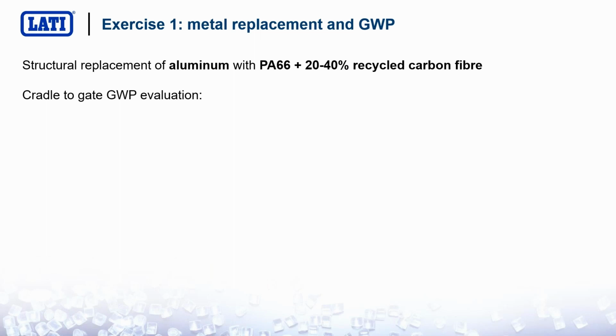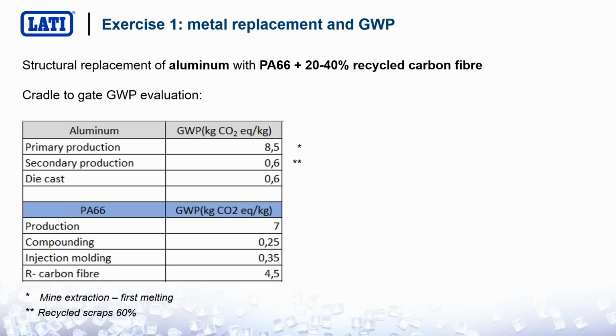Now, let's translate this exercise from structural metal to structural plastic, and let's evaluate the global warming potential reduction. Let's evaluate the cradle-to-gate global warming potential of aluminum and plastic. In the chart you see here, you can see actual numbers which can be found in the literature. For aluminum, I wanted to include 60% of scrap aluminum in a die cast. So the global warming potential for die cast aluminum featuring 60% recycled is more or less 4 kilos of CO2 equivalent per kilo. Remember this number, 4 kg of CO2 equivalent per kilo of aluminum using 60% recycled. I know that today some die cast can be 100%, but let's focus our attention on this 60%.